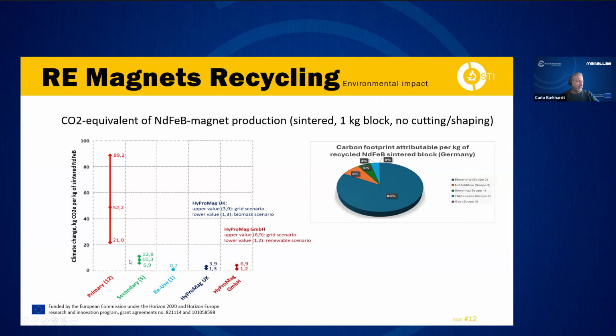You see secondary, there are several around, say hydrometallurgy, pyrometallurgy. Reuse, of course, when you can reuse the magnet, that's environmentally the best. But you see that also the short loop recycling is very close to the reuse scenario, between 1.2, let's say, and 6.9 kilograms of CO2 per 1 kilogram block of magnet.